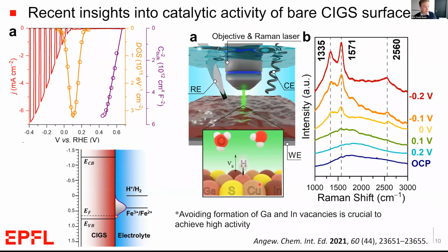And overall, the conclusion is that the surface states are due to gallium and indium vacancies, but these are also the atoms that are participating in the hydrogen evolution reaction. So future work should address avoiding the formation of these vacancies on the surface to improve the photopotential and the photocurrent on these bare CIGS photoelectrodes. So that work is ongoing in our lab. But that's just a small example of how we're trying to engineer one material like this CIGS material.